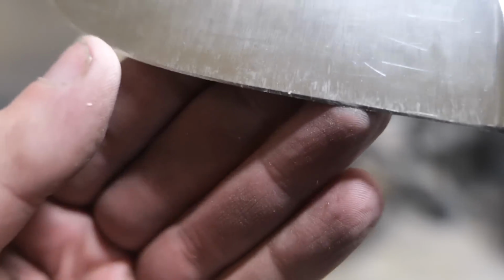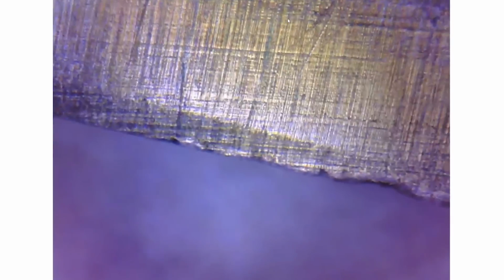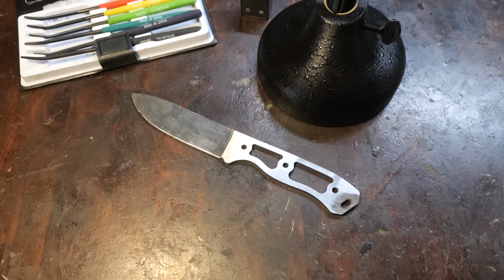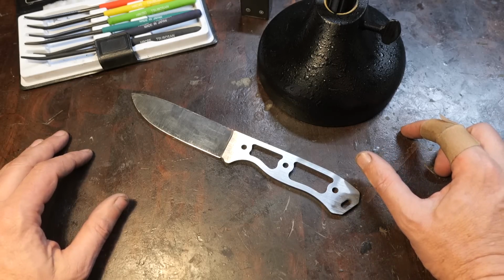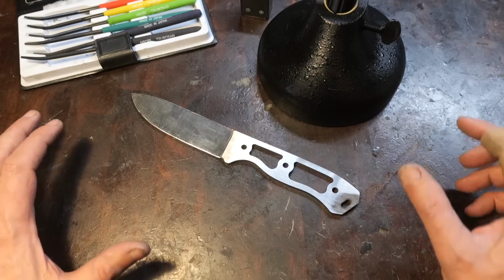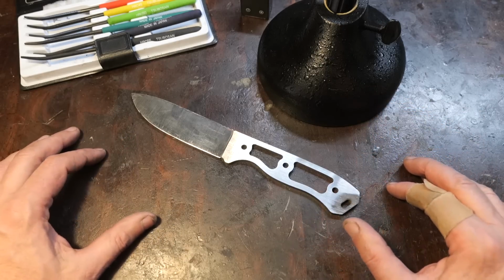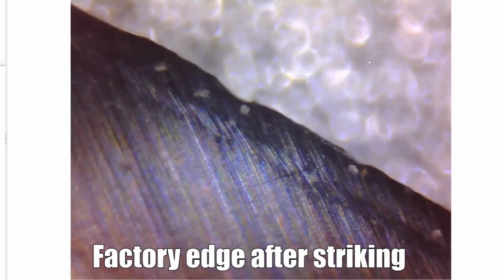Let's go look at it up close. Under the microscope, you can see that the rolling and denting is significant. To be fair, we did subject it to more stress than we did when we were chopping earlier, and it did go halfway through this block without any significant issues. So although it still shaved some hairs, there were some significant snags in paper cutting that couldn't be fixed with stropping. So if you remember, we started to see those rolls appear after chopping against the grain in the knife's